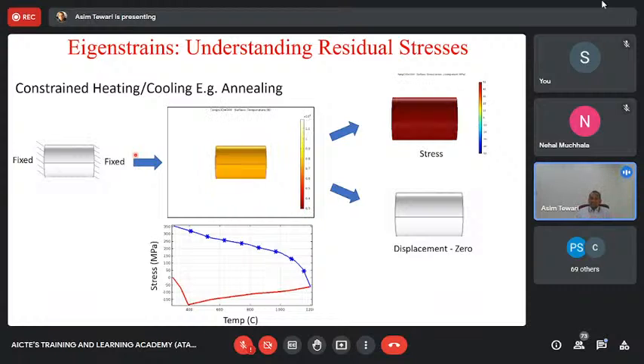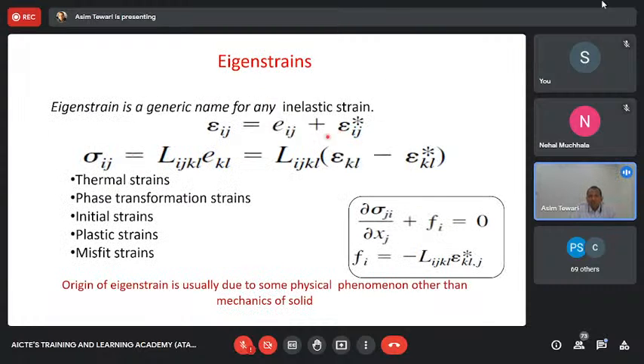And since it has come back to the same fixed state, it should behave just like the one in which it was always fixed to start with. So if it was fixed throughout the process, it should be no different from the one which was free in the beginning, allowed to expand, then you compressed it and brought it to a fixed state. Which means that you did have an eigenstrain which was exactly equal to the expansion. But in this case, you had to bring it down to make the total strain 0. So this eigenstrain was still the same, whether it was free or not free. In the first case, the elastic strain was 0 because the total strain was exactly the same as the eigenstrain. In the constrained case, the total strain is 0 because you're constrained, no expansion possible. That's why the elastic strain has to be minus the eigenstrain.